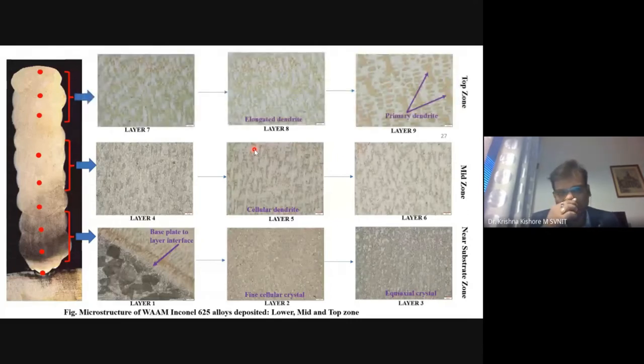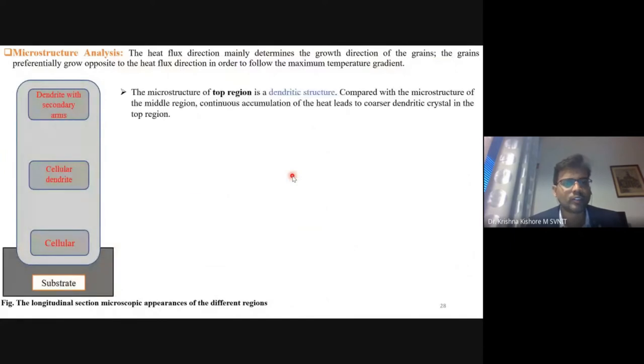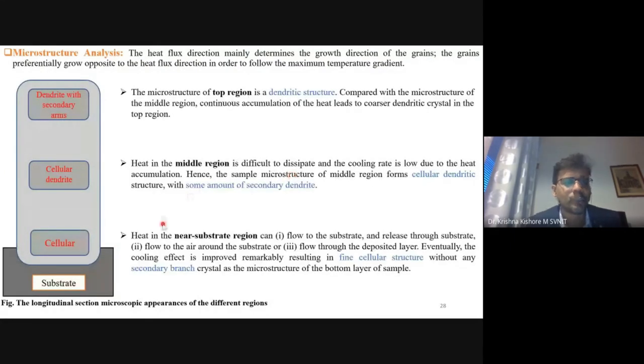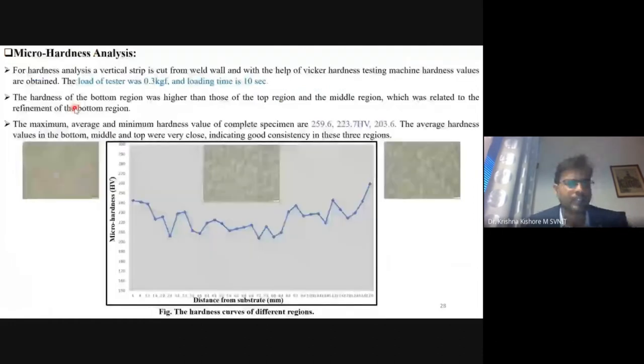And in the top layers, we can see slightly elongated or primary dendrite structures can be obtained. So there is still scope for including different kinds of pulses in order to control this kind of microstructure. So this is a simple representation to show, from the substrate, the cellular structure, the cellular dendrites and dendrites with secondary arms that have been forming.